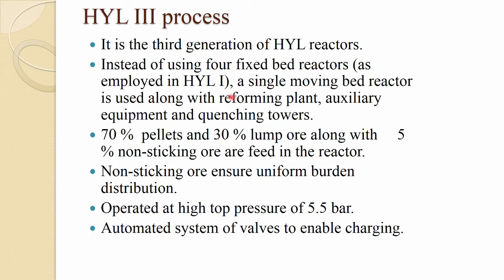The reforming plant is an essential part of most gas-based processes. 70 percent pellets and 30 percent lump ore, along with 5 percent non-sticking ore, are fed into the reactor. Non-sticking ore ensures uniform burden distribution.